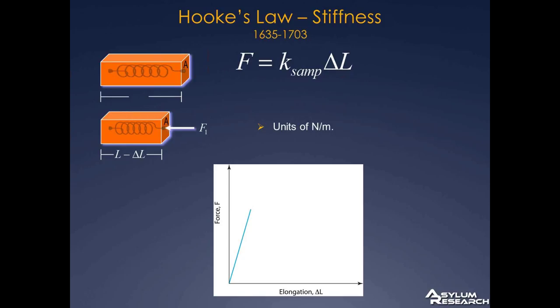Many, many materials follow a linear Hooke's law, at least for small deformations. At some point, they'll start to deviate from that, however. You'll enter what we call the plastic region. If you keep stretching this material or crushing it, you'll get to the breaking point or the yield point. We can also define a couple other points on this graph. This proportional limit is the limit beyond which, if you stretch it past this length, the force is no longer linear. You can also define the elastic limit. What that means is that if you stretch or push it beyond this delta L value here and you return back to zero force, you'll see that the elongation does not return to zero. That is, we've permanently deformed or plastically deformed the material.